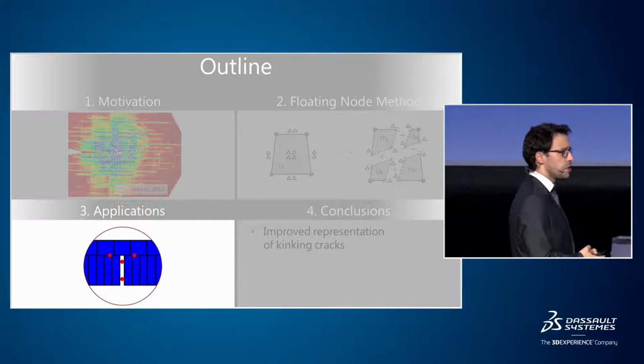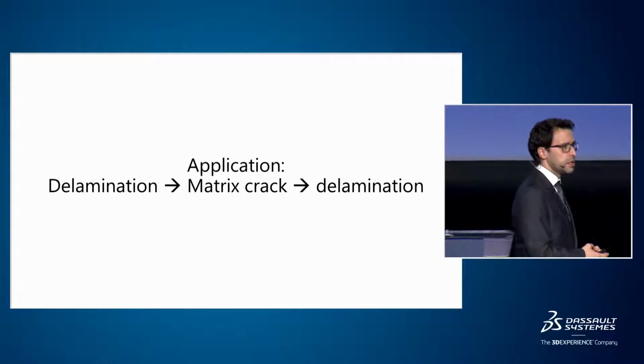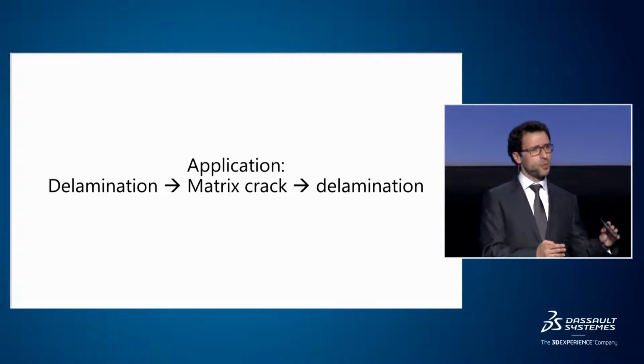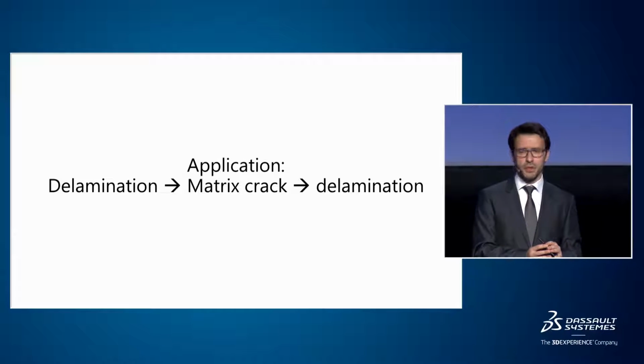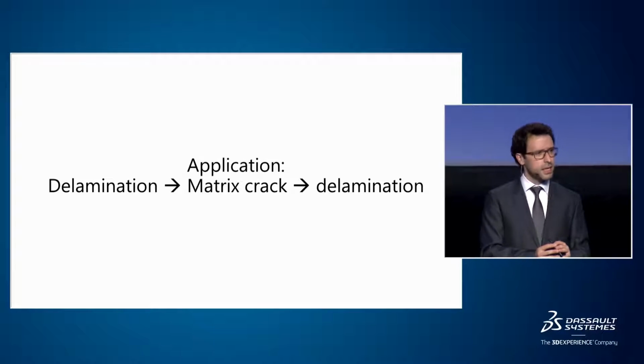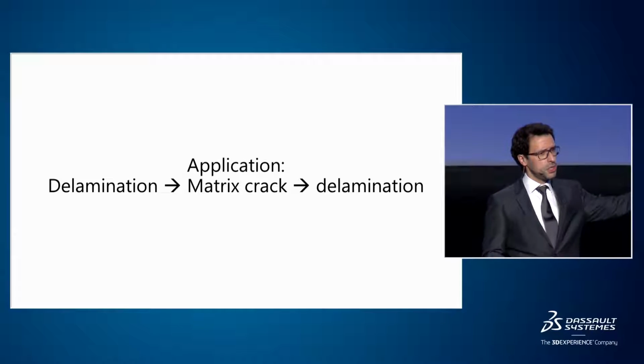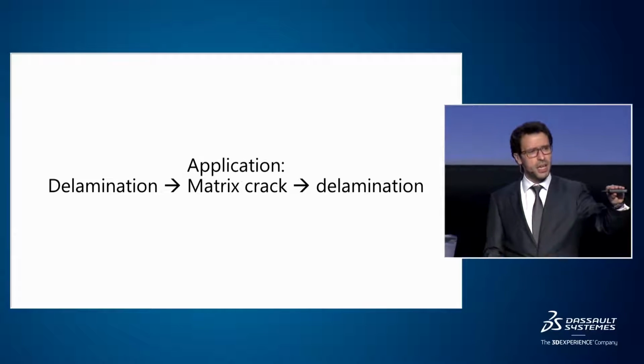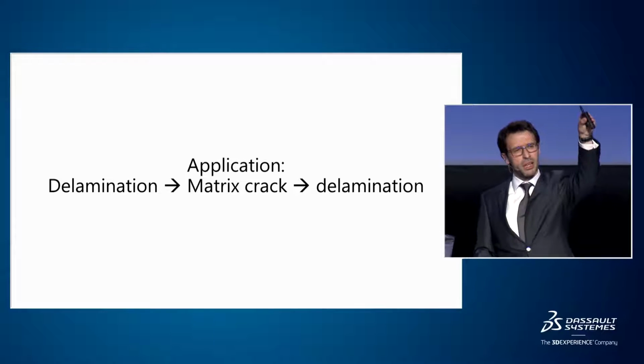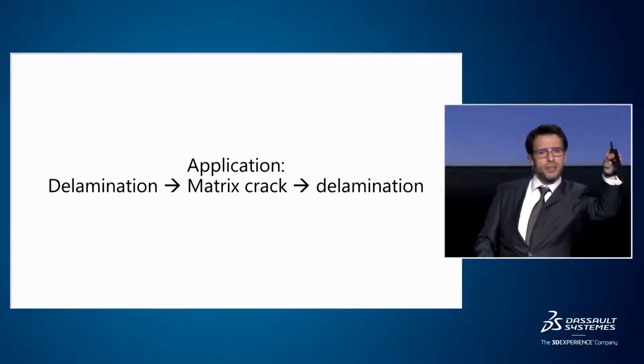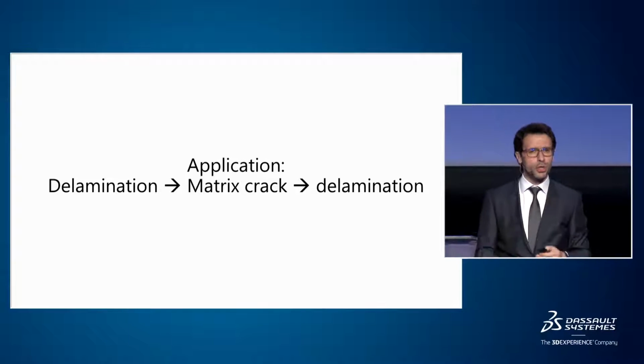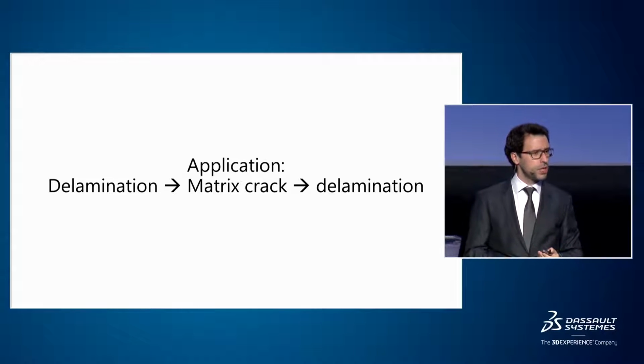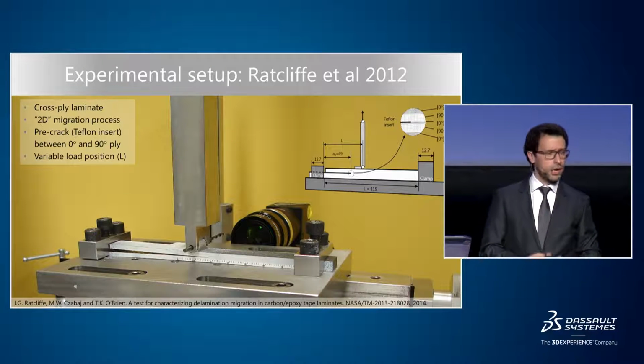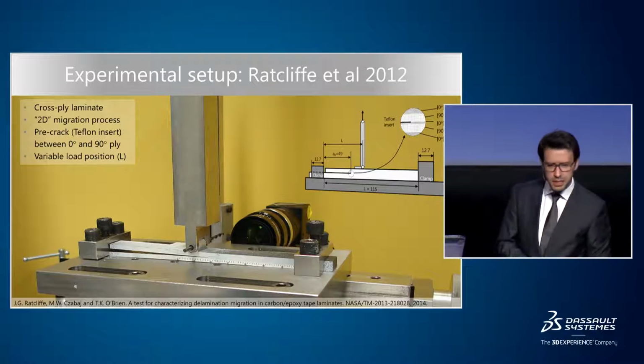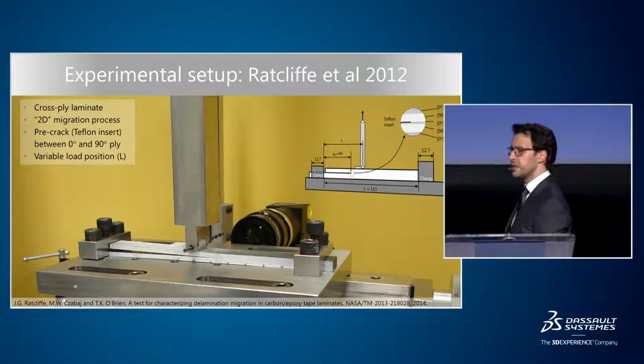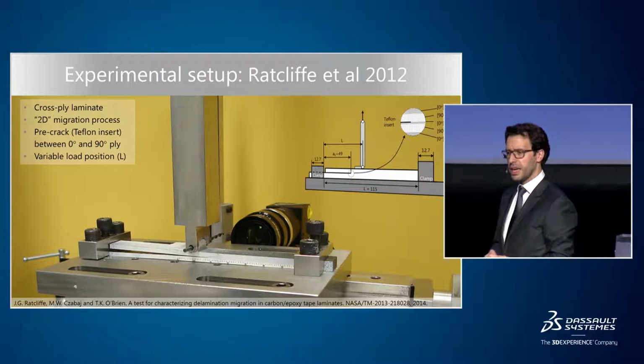The first application that I want to show you is an application which is relatively simple but very difficult to simulate with existing techniques. That's the case of delamination, which is a crack that follows an interface, which migrates into a matrix crack, therefore changing direction, and then changes again direction into another interface, another delamination in a different plane. So I'll compare this against experimental data. This is an experimental setup that was developed at NASA.